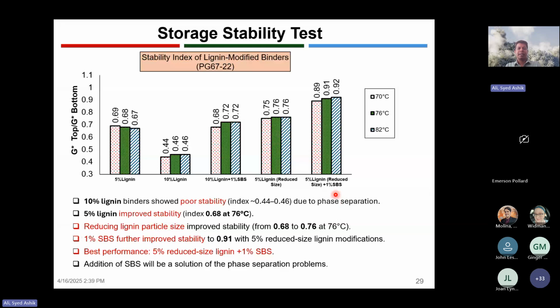So we added 1% SBS, styrene butadiene styrene copolymer, to our asphalt binder, and found out that using SBS significantly improved the storage stability. So that is one of the recommendations from this project: in order to make sure that we have a good storage stability, we may have to use some other type of additives or polymer to improve the storage stability of the lignin modified binder.